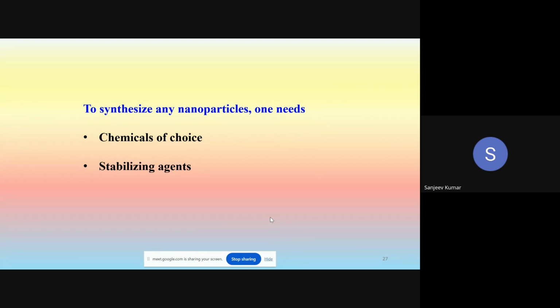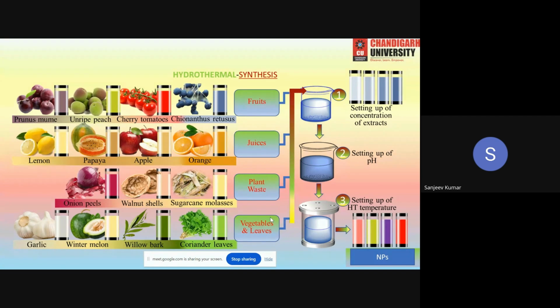In the green method, here in the pictorial, these are some of the fruits, juices, plant waste, vegetables and leaves from which we can easily get an extract. After getting the extract, we mix some chemicals with it. We set up the pH and reaction conditions like temperature and stirring rate. After mixing, we pour them into our hydrothermal autoclave. After a certain period of reaction, within 1 or 2 hours, we get the nanoparticles.